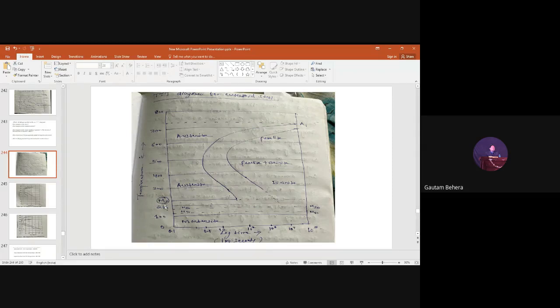But if I choose a temperature of, suppose, 220, this temperature. The moment I keep the steel at 220, I will get martensite within some seconds. Within some fraction of seconds, I will get martensite. It is okay? But that means it is not that 100% martensite will form. Listen carefully. I will get martensite and austenite phase at this temperature. You are getting my point?